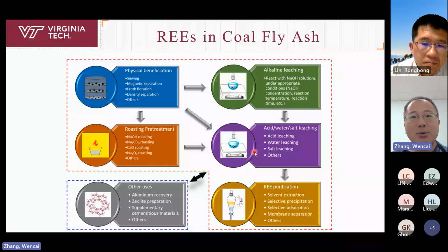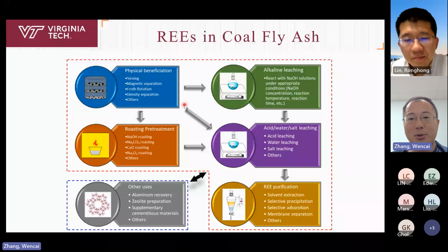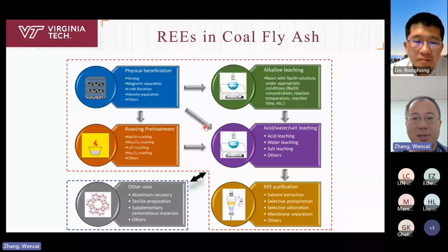Okay, and another process you can do is alkaline leaching. You know that aluminum silicates can be unstable in alkaline conditions. So in this case, if you dissolve, for example, aluminum from the glassy structure, the structure is broken, and then you can do acid, water, or salt leaching to dissolve the rare earth elements. Okay, and a third approach is you can directly go to acid, water, and salt leaching. But as I mentioned, this approach is difficult because rare earths in the coal fly ash are very difficult to release.